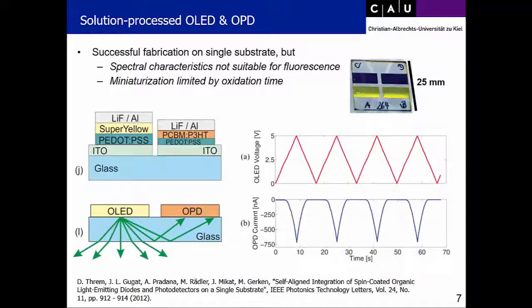And here in this first test, we had just 2 OLEDs and 2 OPDs on a substrate, so the yellow ones are the OLEDs. We operated the OLEDs with a sawtooth, as shown here, voltage, and could measure on the OPDs a current as we would expect, which is just caused by the effect that some of the light from the OLED enters the OPD. We also did refractive index measurements with this.